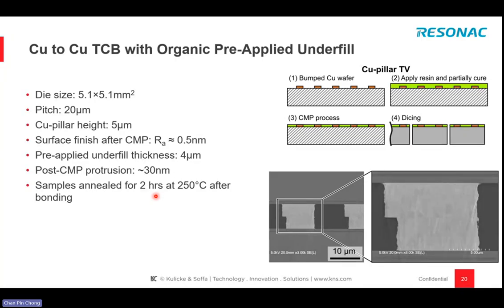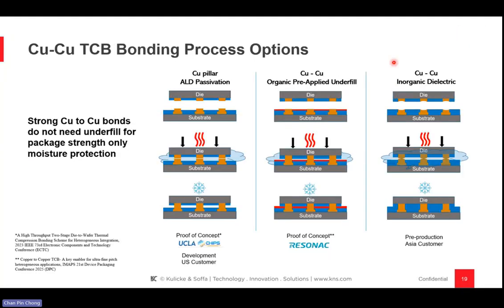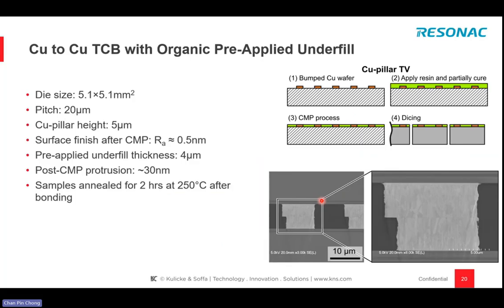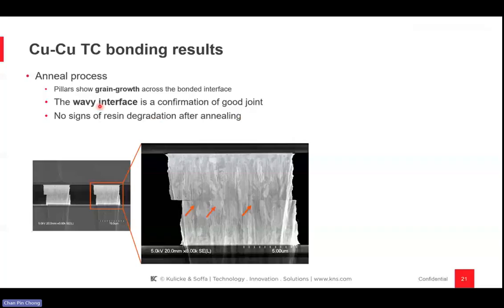So this is one of the methods which I mentioned. This is method number 2, and this is what we've done. Here you can see that after the new process, the copper shows grain growth, okay? And the wavy interface is a good confirmation of a good joint between the two surfaces of copper. And there are no signs of any resin degradation after the annealing. All right, so this experiment works quite well,